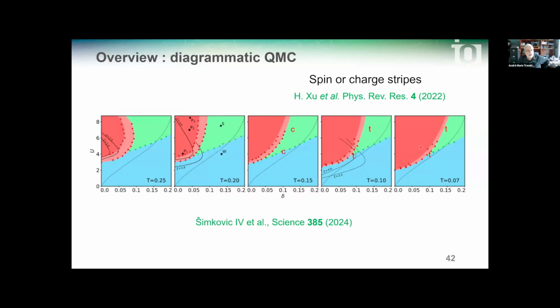The maximum of compressibility observed in cold atoms is indicated with these letters C here, and they correspond to TPSC. And with a few calculations with TPSC, it is shown that this maximum is not far from that pseudogap phase boundary.